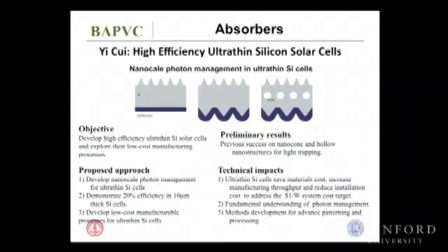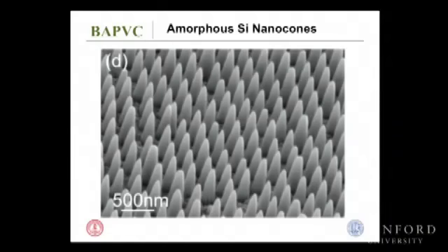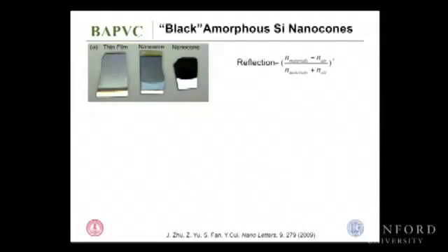So there's a lot of interesting ideas really built on our past research. Let me give you an example of how this idea came about. In the past, we have been working on amorphous silicon, this type of nanocone. We know how to generate this nanocone. You see their separation is roughly 500 nanometer, and the diameter is a couple hundred nanometer. This is within the wavelength of the sunlight photons you care about. So this really allows you to manage the photon in a different way from traditional solar cells. Looking at the nanocone and the amorphous silicon thin film about 1 micron thick, you see the nanocone after etching become completely black.